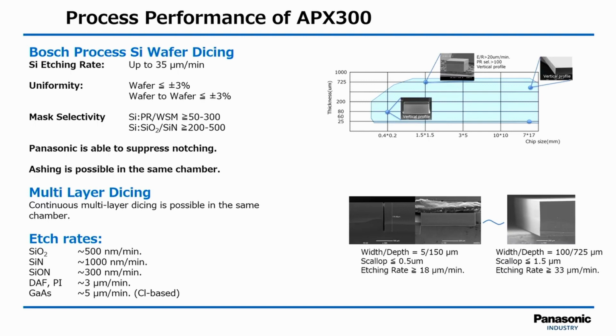Ashing to remove the photoresist, it's all integrated in the same chamber, so no need to remove the wafers or purchase additional equipment. It's possible for us to dice multi-layer wafers, all in the same chamber. You can see on the bottom right examples of, well, the first one is an example of a relatively high aspect ratio, so 5 micrometer opening and 150 micrometer etching depth, very small scallops, 0.5 micrometer, and an etching rate of 18 micrometers per minute. Whereas, as I said, we can go all the way up to 725 micrometers with slightly larger scallops, 1.5 micrometers, and still provide a, in this case, it was a 100 micrometer street width, so relatively fast dicing speed of 33 micrometers per minute.